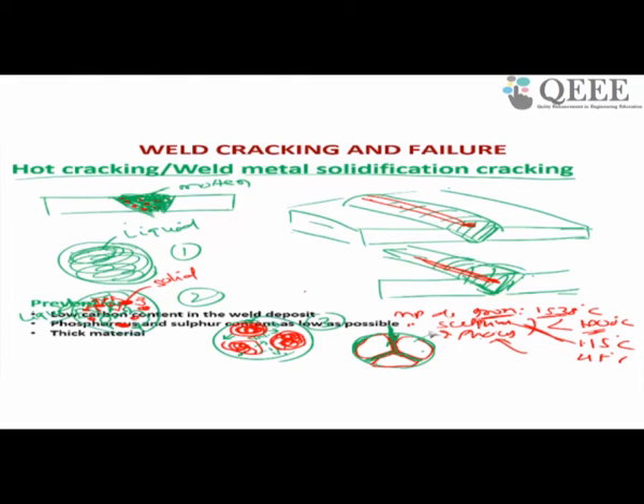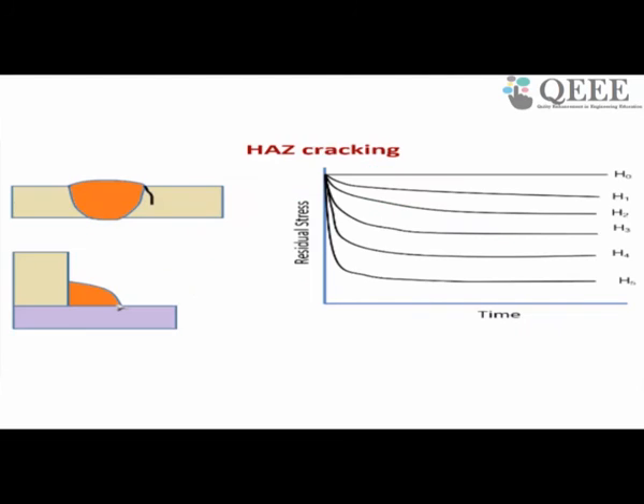Okay, so how to prevent solidification cracking? You should avoid phosphorus and sulfur in your material. You should avoid carbon in your material, and you should avoid thick material. Then you will not get this kind of solidification cracking defect. Next one is heat affected zone cracking. What is heat affected zone cracking?